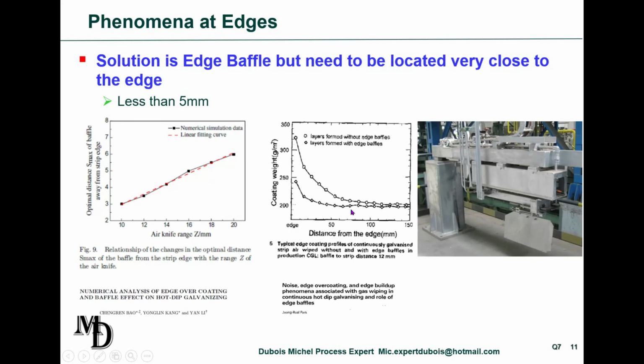The question is always, how far should that plate be located from the edge strip? This is more or less given by this excellent Chinese work. They worked by CFD, but I am sure that it's absolutely correct. It shows here the optimum distance versus the air gap range, and practically it means that you have to be lower than 5 millimeters away from the strip edge to really minimize the coating over thickness.